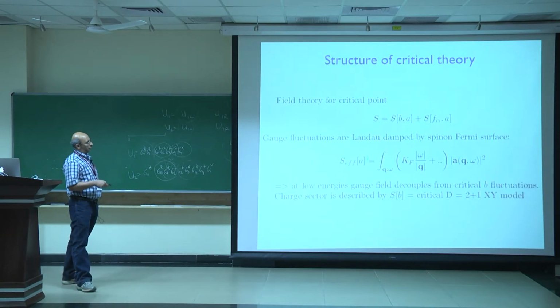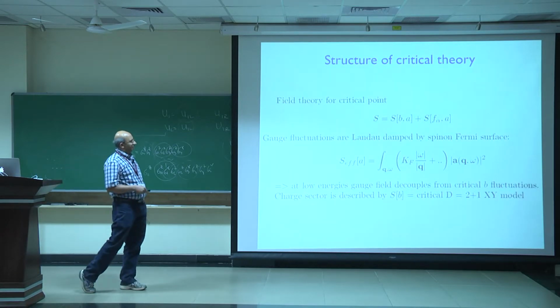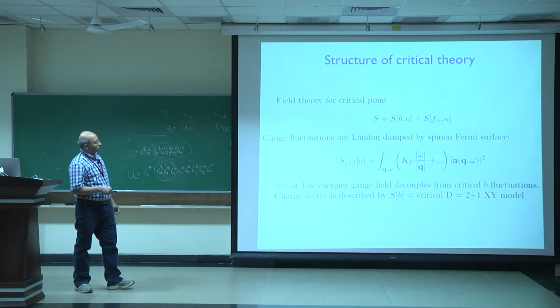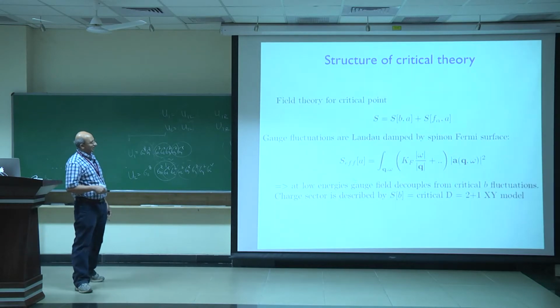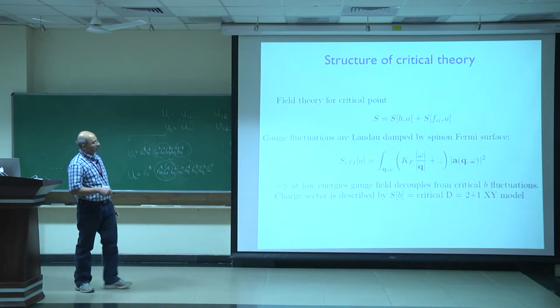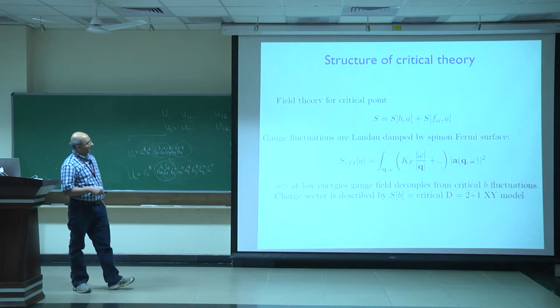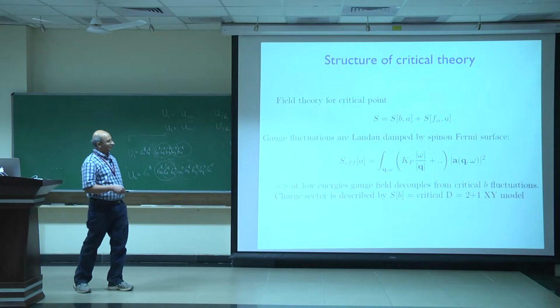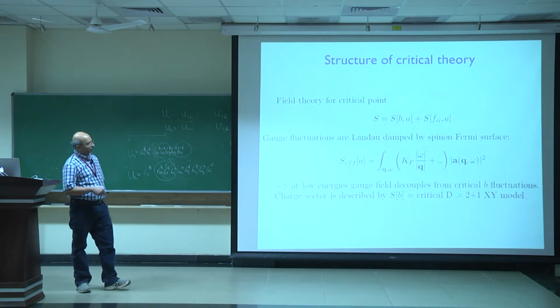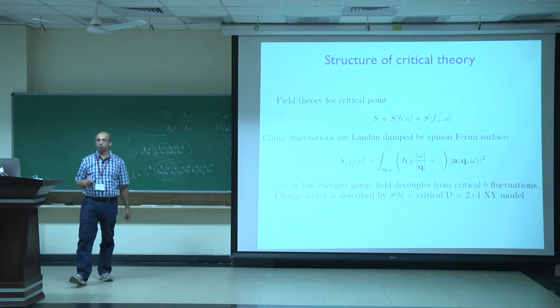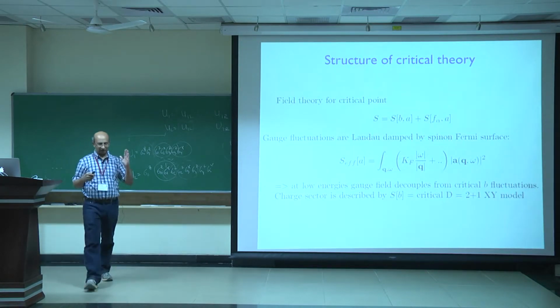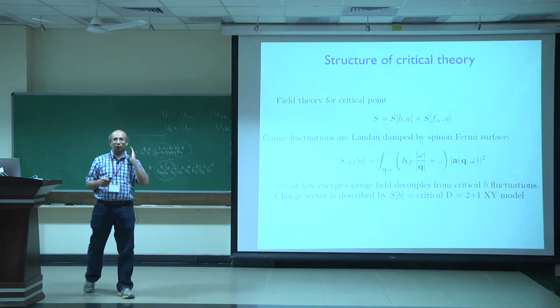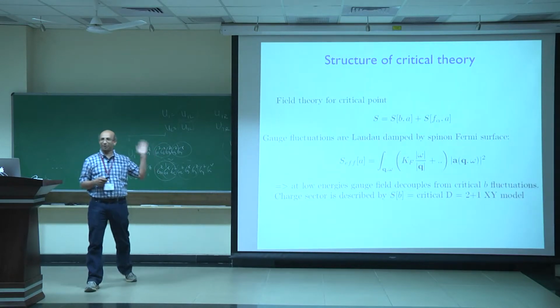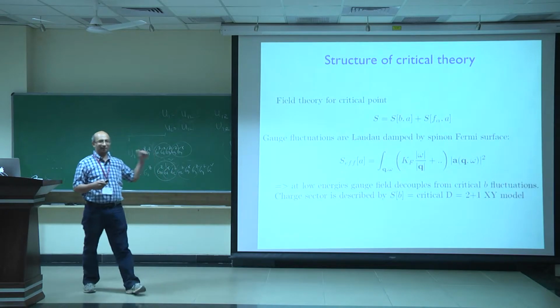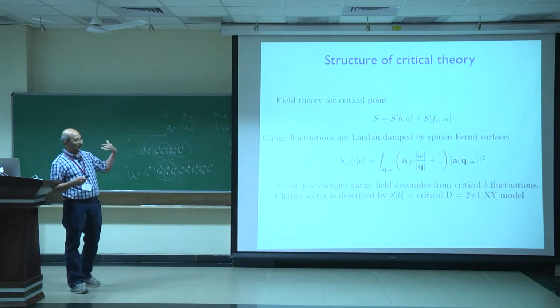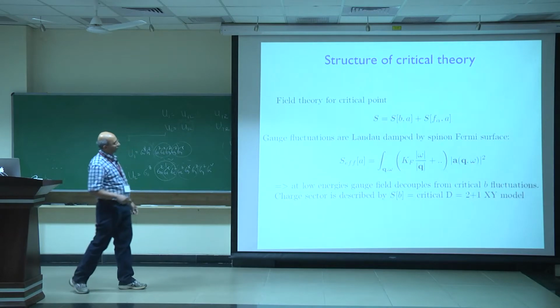Now, the presence of this kind of Landau damping, which comes from the Fermi surface, means that this gauge field essentially dynamically decouples from the critical boson fluctuations near the Mott transition. And the reason is that the critical boson fluctuations are described by a 2 + 1 dimensional XY model, right? Because it's a superfluid insulator transition of bosons at integer filling. And since, of course, all of you have read Subir's book, you know that that's described by a relativistic quantum field, a relativistic conformal field theory. That is the 2 + 1D XY model.